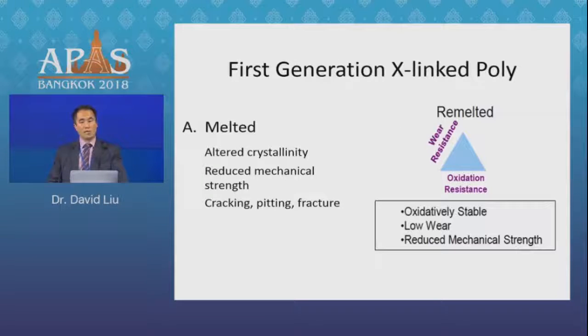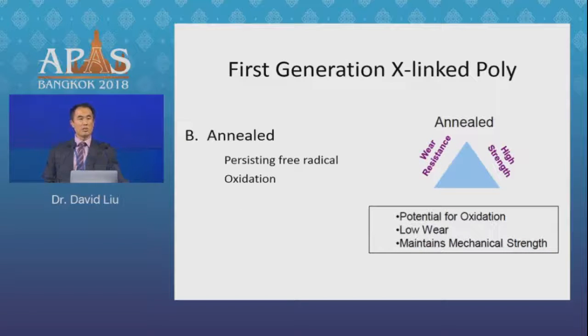So to try and deal with the free radicals, there were two processes implemented. The first was to heat the polyethylene above its melting temperature. This process was very good at getting rid of the free radicals, but again it reduced the crystallinity of the molecules themselves and thus reduced the mechanical strength. So you kept the wear resistance improvements and improved the oxidation resistance, but you compromised on the mechanical strength. The alternative was to heat the polyethylene below melting temperature. Here again, you kept your wear benefits and maintained your mechanical strength, but the process was nowhere near as good as heating above melting temperature in getting rid of the free radicals, and so the polyethylene remained somewhat vulnerable to oxidation once it was implanted or removed.